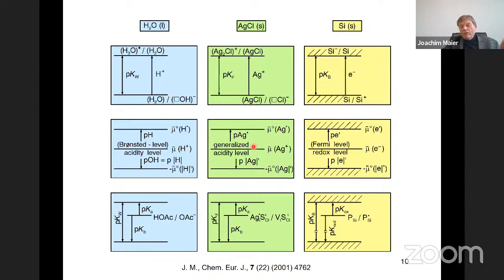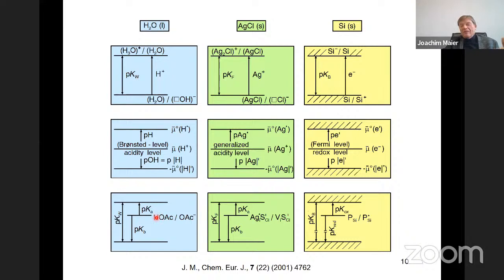For those interested in a point-defect-type acid-base concept for ionic crystals: you just count the point defects, because their concentrations in equilibrium reflect acidity and basicity the same way as electron concentrations reflect redox behavior. A phosphorus dopant within the band gap excites an electron to the upper level; analogously, acetic acid excites a proton to the upper level. You can group all acids and bases in terms of free energy levels — and the same for silver chloride with impurities. There is a far-reaching isomorphicity at work.